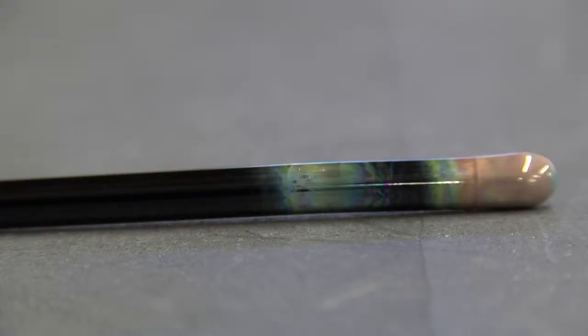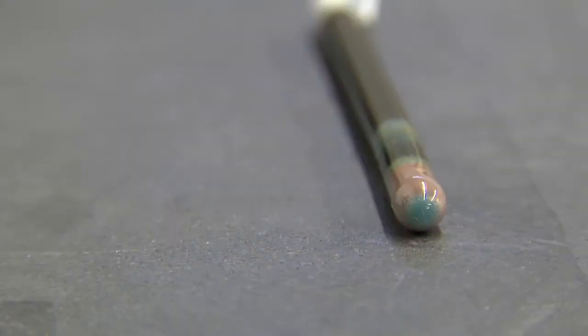If the rod is light sky blue or has a metallic sheen, that means the flame is reducing and the propane needs to be decreased. Note that the propane to oxygen ratio depends on the torch you are using. If the rod is sky blue, the flame is very reducing and should be adjusted by decreasing the propane pressure at the regulator, for example, from 4 pounds to 2 pounds. If the rod has a metallic luster, try decreasing the propane on the torch or at the regulator in 1/4 pound increments until you are able to heat the rod without a color change.